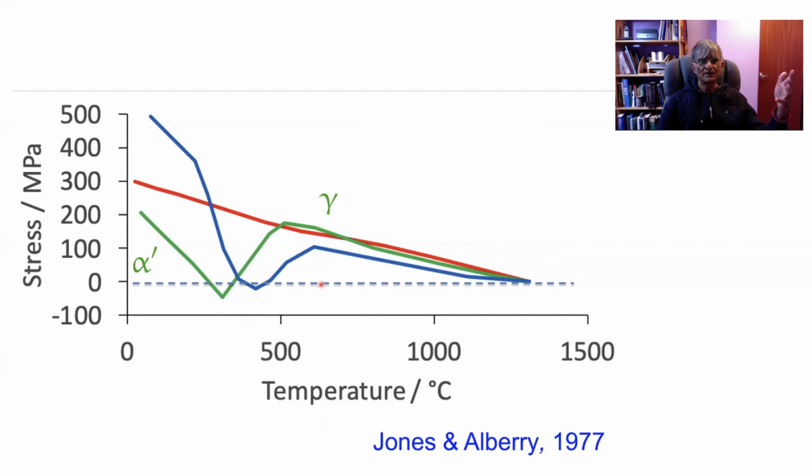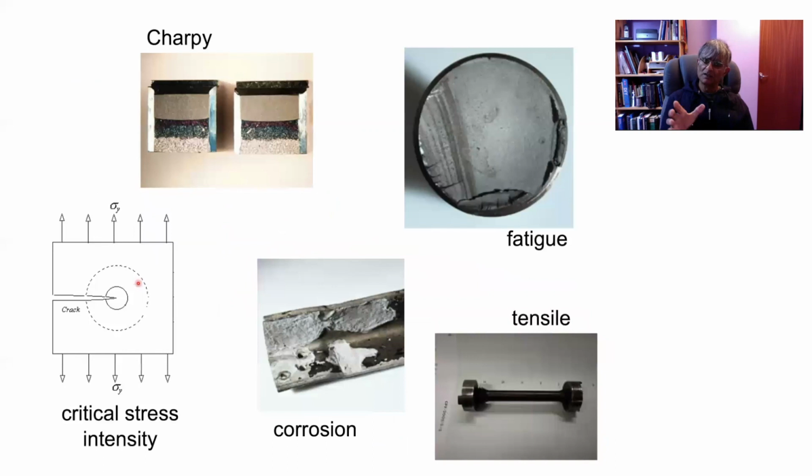So the clue from this is that suppose you could reduce the transformation temperature sufficiently so that this point ends up over here, then the problem is solved. And bear in mind that the transformation is actually happening inside the welding alloy, not inside the adjacent steel. And because it's a welding alloy, you're only using relatively small quantities, so they can actually be expensive relative to the basic steel. But it also means that a vast range of other properties must be achieved in any alloy design. And there's no time to go into that, but all of these properties you would need to think about and to calculate using techniques such as neural networks and so forth, in addition to controlling the transformation behavior.